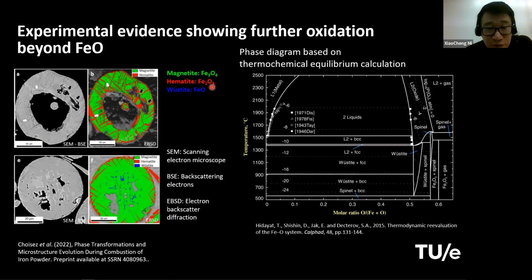And if we look at this phase diagram, the x-axis is the molar ratio of oxygen, and the y-axis is the temperature. You can see there are different phases this mixture between oxygen and iron can go into. And in the middle, you have this two-liquid region where your liquid iron and the liquid oxide, which we approximately understand as liquid FeO, are immiscible, so they are two separate phases. And we think that in the early part of the combustion, you just absorb more and more oxygen, so the particle keeps oxidizing in this phase, and the temperature keeps increasing up to a certain point.